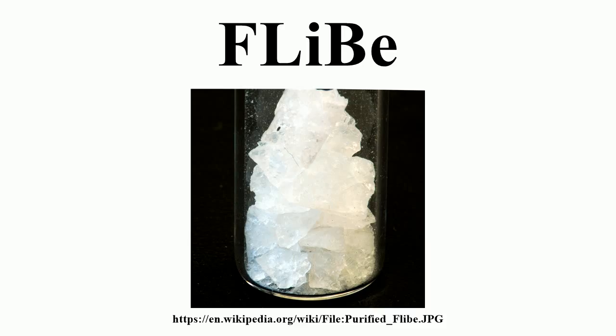Lewis base. Lewis bases, such as the alkali fluorides, will donate fluoride ions to the beryllium, breaking the glassy bonds which decrease viscosity. In FLiBe, beryllium fluoride is able to sequester 2 fluoride ions from 2 lithium fluorides in a liquid state, converting it into the tetrafluoroberyllate BeF4-2.